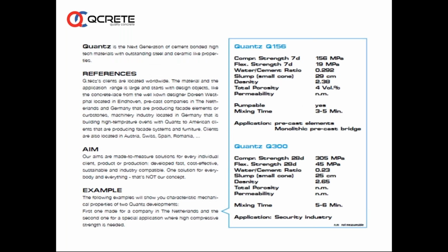Going forward, there are specific companies, especially some companies in Germany, where they have made proprietary ultra high performance concrete, where you can see here the product is called Quantz Q156 with a compressive strength at 7 days of 156. You can see water cement ratio 0.292, slump is 29 centimeters, and porosity, permeability is not measurable. Concrete is pumpable. You have to mix for 5 minutes, and then it can be used for precast elements.